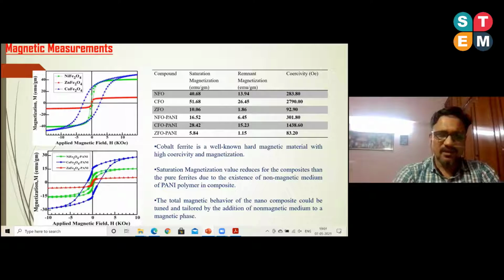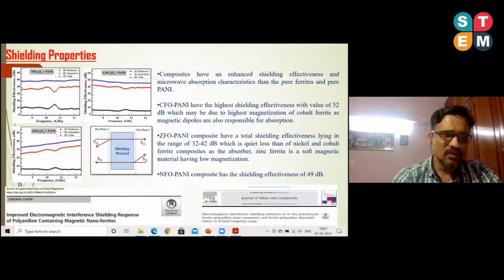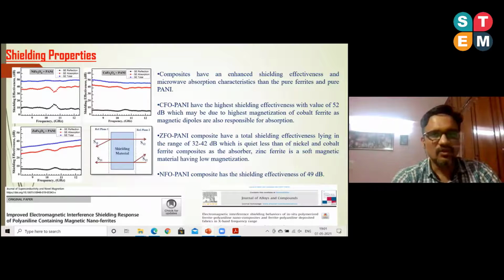So after the filler, we're making the composite with the conducting polymer, because I have taken PANI as a conducting polymer because of its high conductivity, and then make the composite and study the EMI shielding properties. So the total shielding effectiveness of the nickel ferrite and PANI composite material is in the order of 50 decibel, and the cobalt ferrite is also showing near about 50 decibel, while zinc ferrite and PANI show a little bit less shielding effectiveness. So in this work, we can conclude that an appropriate amount of ferrite in the PANI composite can work as an effective shielding material.